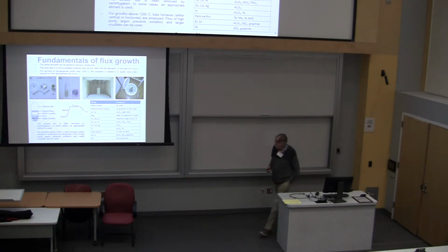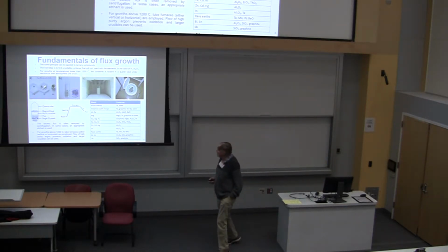Okay, so here's a picture of how we often do things, and this is an example of growing cerium rhodium indium, using cerium and rhodium in excess indium. So this is just the elements, cerium, indium, and rhodium in an alumina crucible.